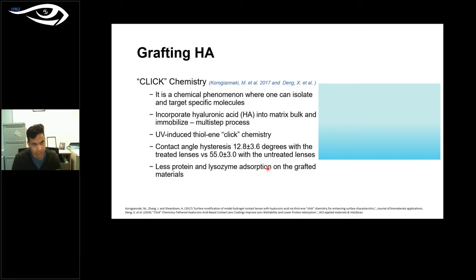Click chemistry is a special chemical phenomenon where one can isolate target specific molecules. If I were to put this in the contact lens field, we want certain molecules to be in certain positions in our lens matrix. Hyaluronic acid is one particular material we want to be available in the lens matrix. In general, hyaluronic acid is used in contact lens materials, but in order to get this into the lens matrix, you need to take several steps. By using click chemistry, the material scientists were able to tether, or place, these hyaluronic acid molecules at one particular area and then lock it there.